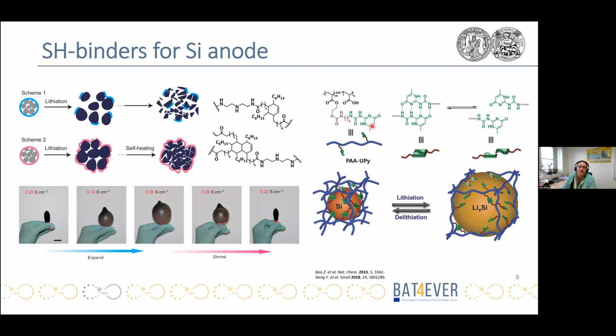Another interesting example is presented here on the right. You can see a self-healing binder where the quadruple hydrogen bonding supramolecular UPy groups are used in order to introduce the self-healing function. Here, a very small amount of the UPy groups have been incorporated into the linear chains of polyacrylic acid, PAA. Polyacrylic acid has been widely investigated as a binder for silicon electrodes also on its own due to the presence of the large number of carboxylic acid groups which are capable to undergo hydrogen bonding among each other and with the silicon anodes. And this provides a good chemical stability of the electrode during the cycling.